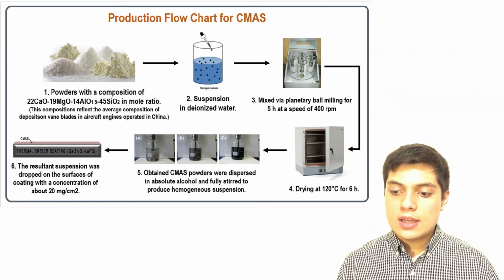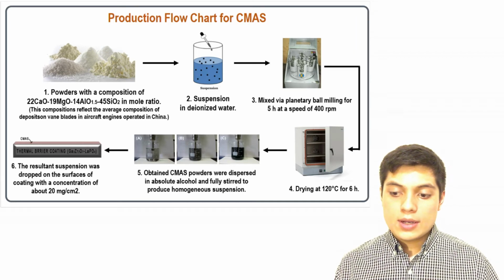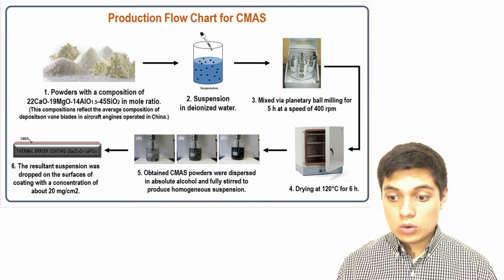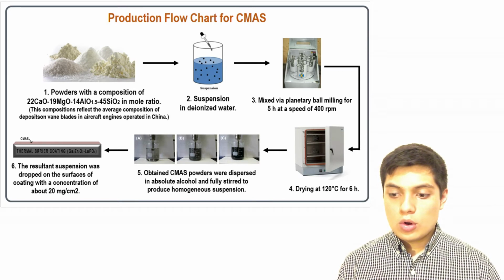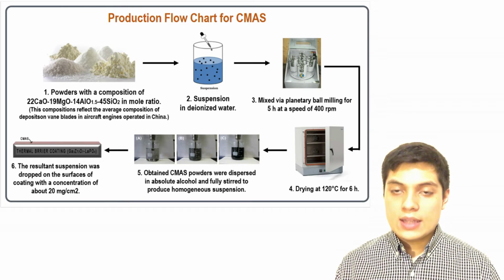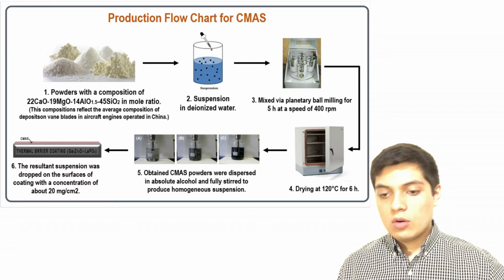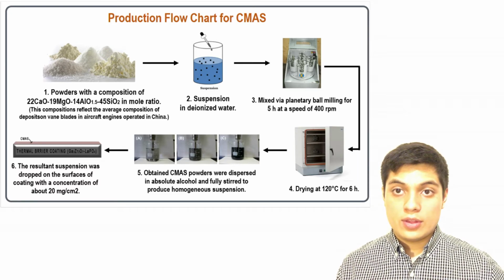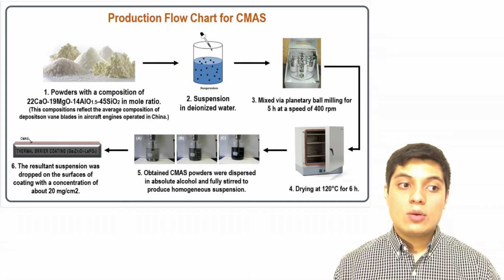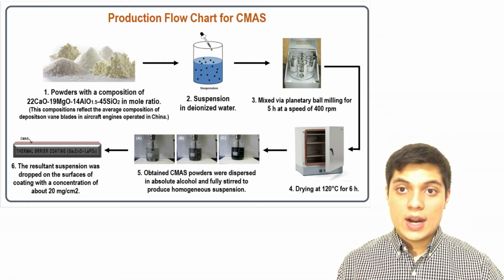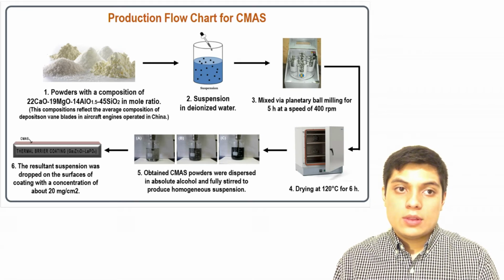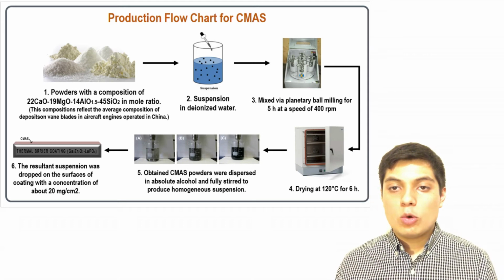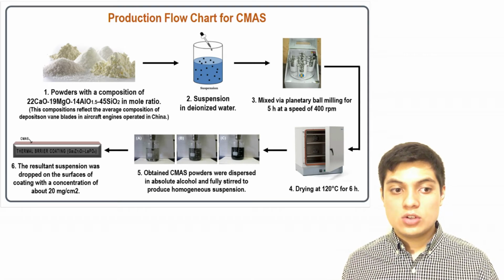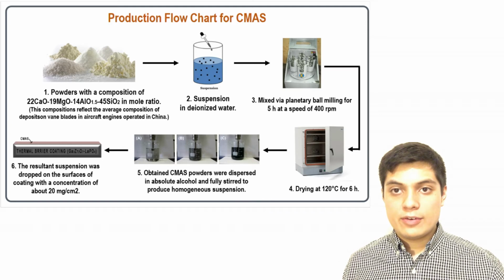Then the obtained CMAS powders were dispersed in absolute alcohol in order to produce a homogeneous suspension, and then they were poured over the surface of the thermal barrier coating. When the alcohol dried, they obtained a completely homogenized surface over the whole thermal barrier coating.